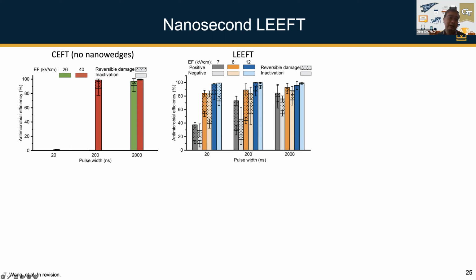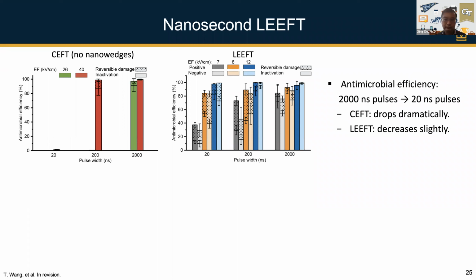We also show that on the chip device, we really observe this phenomenon. At the same time, on the other side, we notice that with the LEEFT, we actually can push the treatment time all the way to 20 nanoseconds. As you can see here, with 12 volts, it's about 100% removal, and even when the voltage is a little bit smaller, the electric field strength is smaller, you can still achieve fairly significant microbial inactivation.